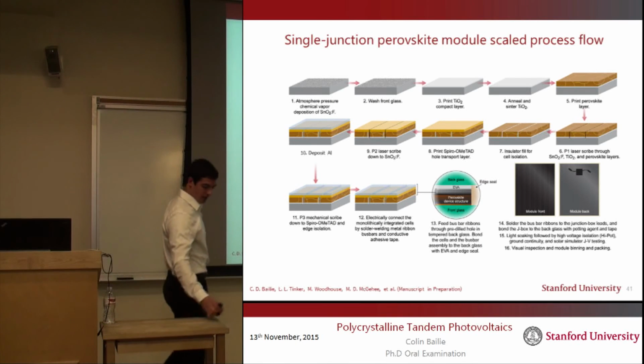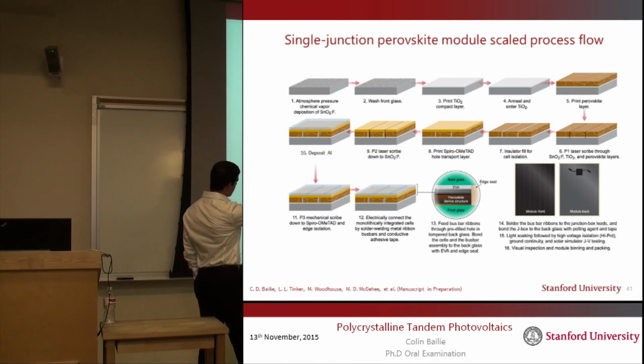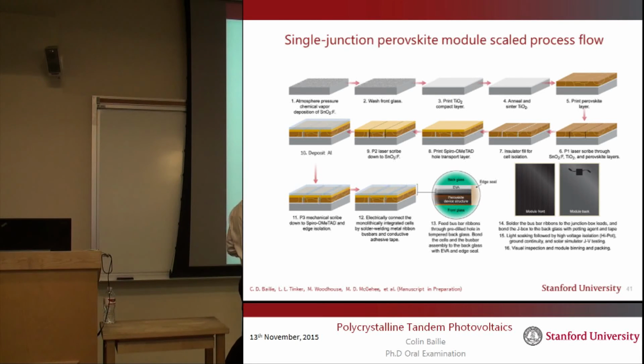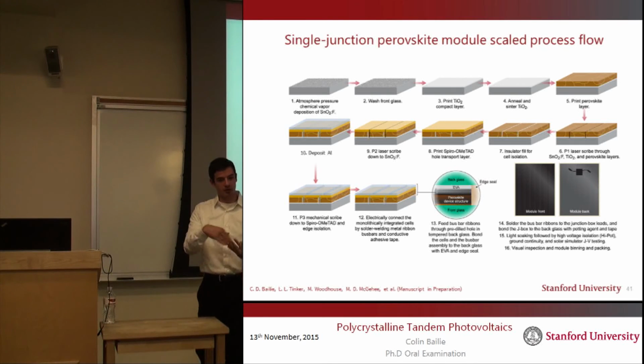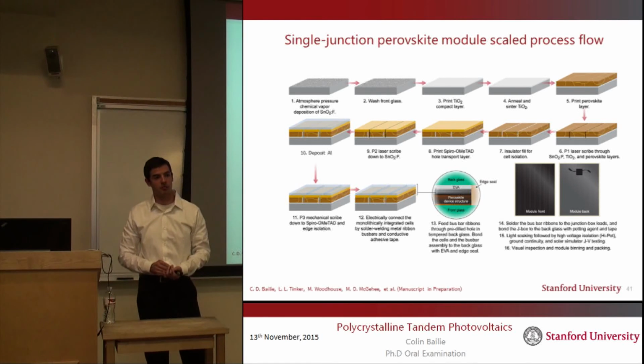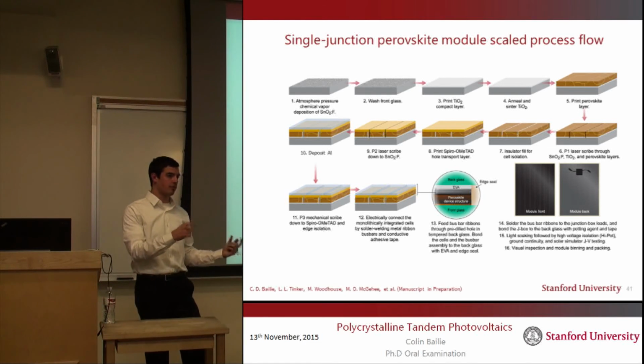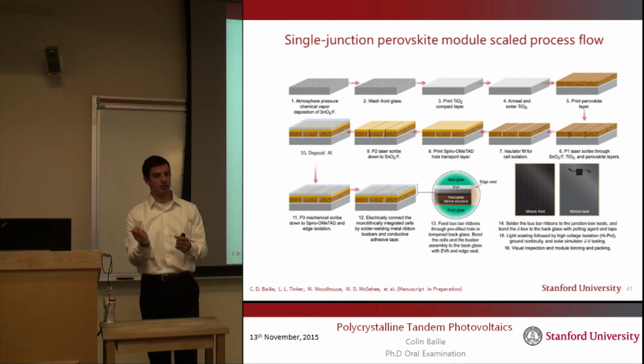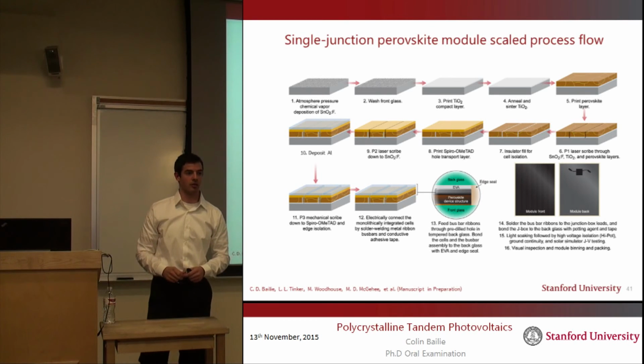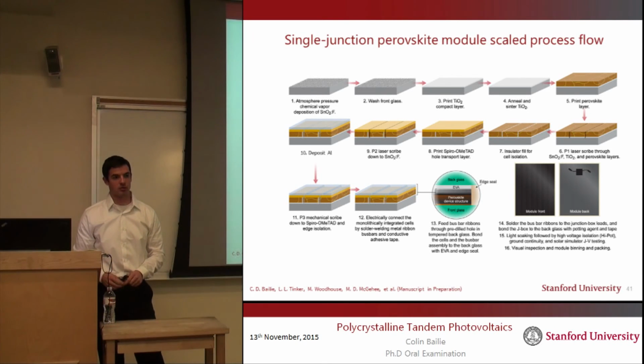So a common strategy when you're depositing things and defining cells in a monolithic style for thin film integration is that you can put in an insulator that fills in these gaps, and that provides an edge seal for this cell. And then when you have a glass flat sheet, you have to use something like a rubber seal for the module to seal that edge.